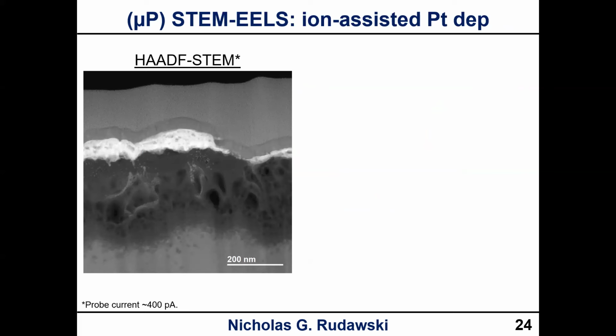because you can do microprobe STEM EELS as well. So if we look at the HAADF STEM image, what this is is platinum that was deposited on silicon via ion-assisted deposition. And so this actually has a very unique microstructure. Basically, everything from the chromium above, the chromium and the E-beam platinum, that's all part of the sample prep. Everything else is actually the sample itself.